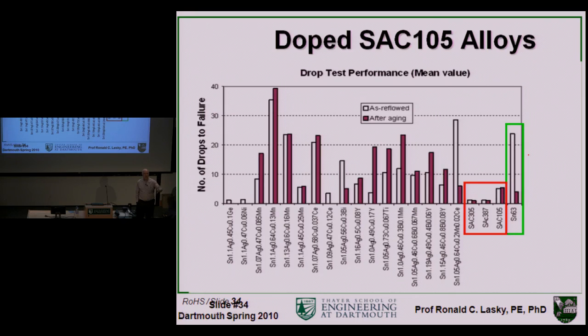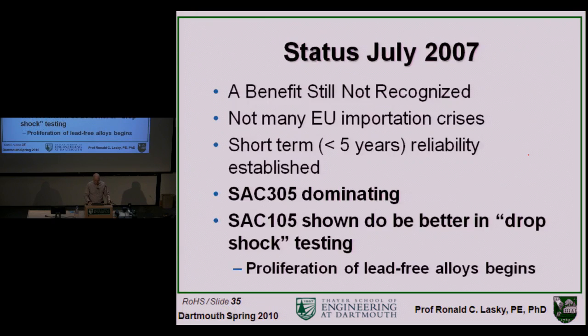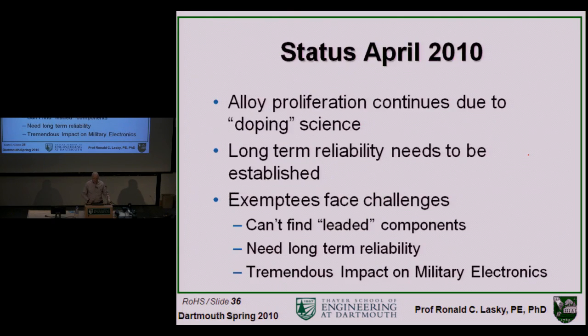In other words, there was only tin lead solder, pretty much, until lead-free came around, and then we hoped it would be SAC 305, but now there's SAC 305 and 105. Now there's SAC 305 and 105 with dopants in it, and we still haven't converged on it. And so most of us are hoping that we'll be able to converge on a few families of solders for lead-free, but at this point we're still kind of exploding in what we're looking at. So I think that's pretty much all of what I said. So the status of today, I mentioned this doping. Long-term reliability still needs to be established.